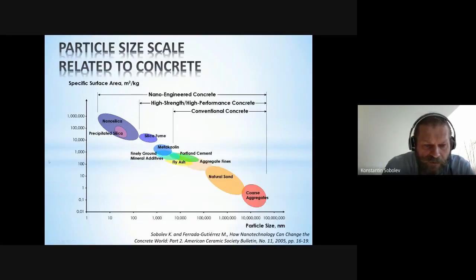If you look at this relatively old diagram, which we proposed back in 2005, of specific surface area and particle size, we can see that all concrete materials follow this straight line. Conventional concrete is what we can do with a conventional set of aggregates, Portland cement, and potentially fly ash. This is what I was discussing at the very beginning of my talk. When we have new components like silica fume and metakaolin, we were able to achieve high strength, high performance concrete in a relatively easy way.